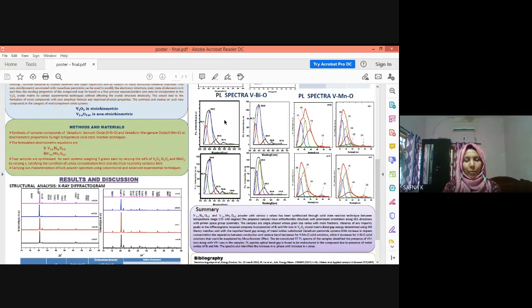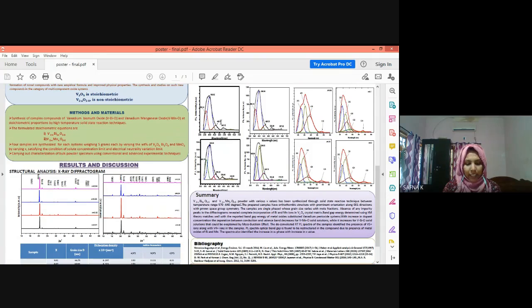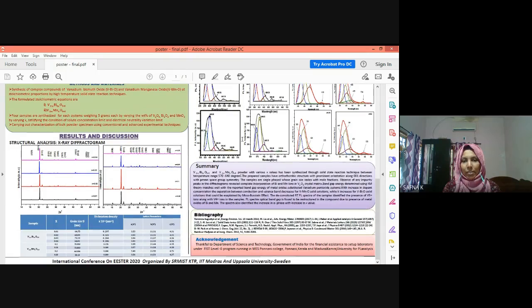And the 460 nanometer emission has an energy higher than the bandgap energy and might be due to the recombination of electrons from higher levels of the valence band and conduction band. The low intensity indicates oxygen deficiency related defects in the crystal. All these emissions are relatively strong and broad, and this is an extremely desirable feature required for different sensor applications.